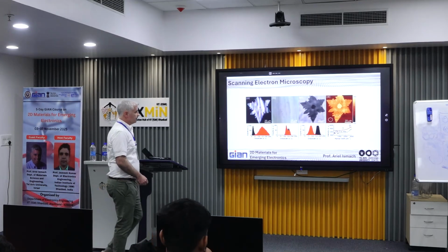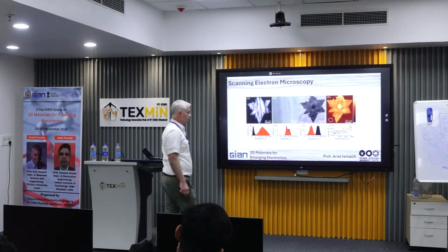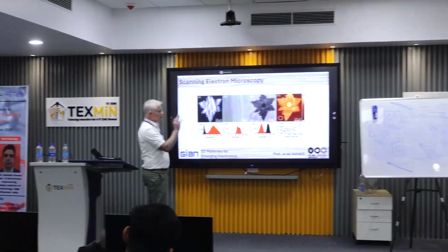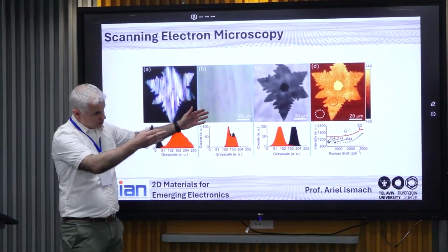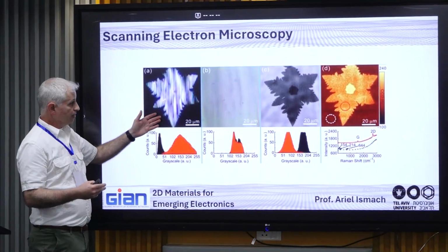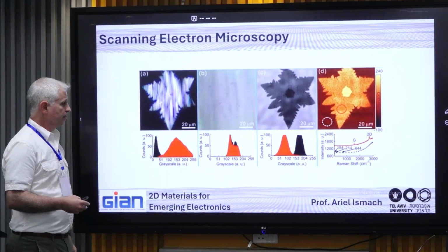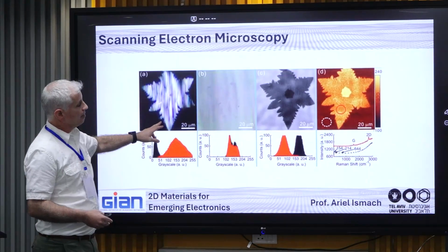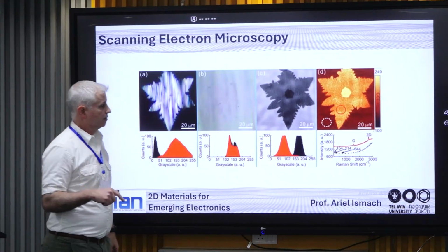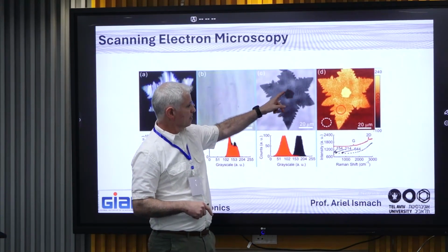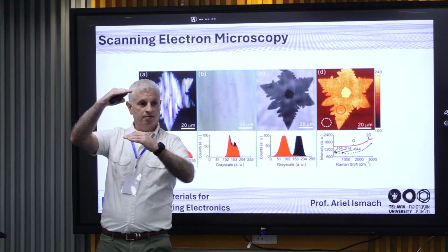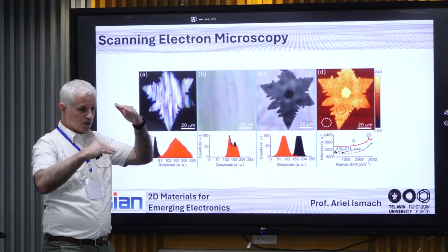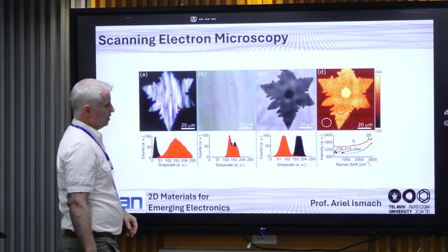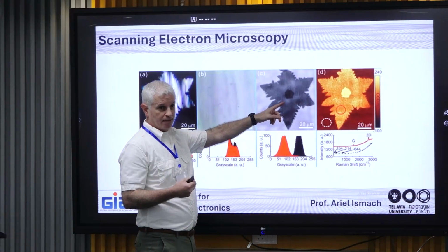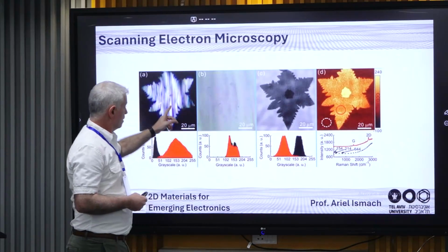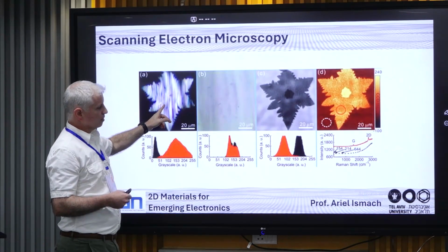Now again, compared to the methods that we saw, you see here the same domain on copper. Here we have the bright field optical microscopy, where we don't see almost anything, and the dark field, where we can detect where the graphene is. And also in the SEM we see it, but in the SEM we now add another piece of information. What do we have here? This is an added layer, a second layer that actually usually goes below. A second layer of graphene that you can identify. Look how sensitive it is to the number of layers. In dark field, most of the time you cannot see it.